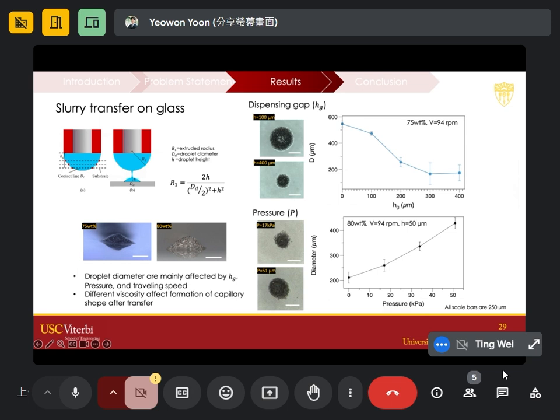Another factor is the pressure. If you increase the pressure, you have more material coming off the plunger, and therefore a larger droplet. So we can see the gap: if the gap increases, the size of the droplet decreases. Where the pressure increases, the size of the droplet increases.